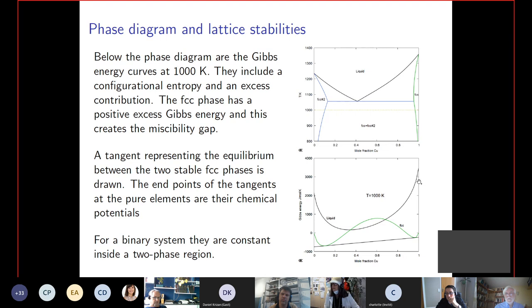The relation with the Gibbs energies is that if you take, for example, a temperature here, you have a Gibbs energy curve for the liquid, you have a Gibbs energy curve for the FCC phase, and here you see the miscibility gap: it prefers to separate into two phases, one with the composition silver-rich here and one copper-rich here. And at this temperature, the liquid is not stable, so it is above the solid phases. And you also have the chemical potential, which is important. That is basically the tangent curve here. So the end points of this are the chemical potential of copper and the chemical potential of silver at this temperature.